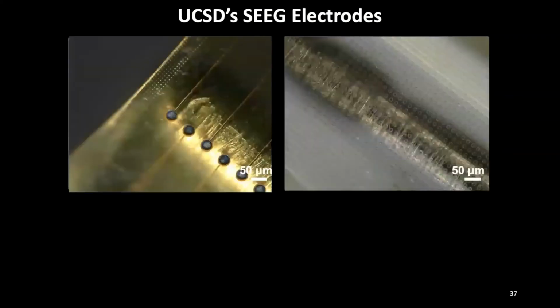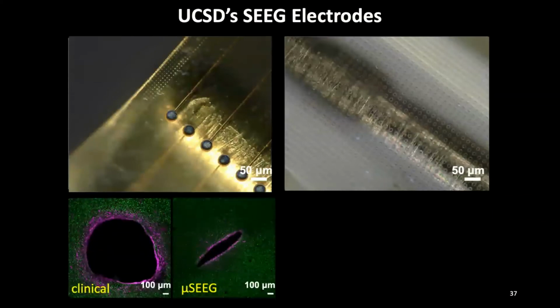Now, if we look closer at the tips of the electrodes, we're looking here at a stainless steel stylet that usually hardens a clinical electrode. In this case, it's hardening a polyimide electrode for insertion into the tissue. This is the front, this is the back. And if we zoom in, we start seeing the micro contacts on the top left. There's an array of holes at the very tip so that we can have better adhesion between the two polymer layers at the surface to prevent ripping. And this is the back of the electrode in which we release sacrificial layers inside so that the electrode becomes inflatable.